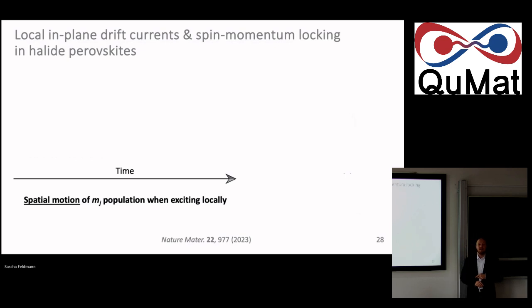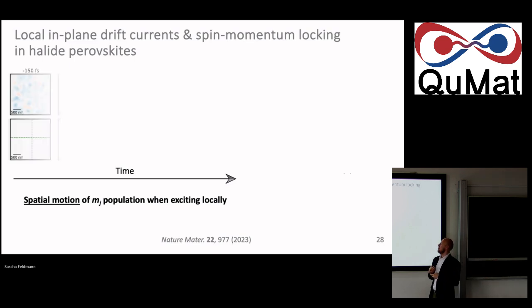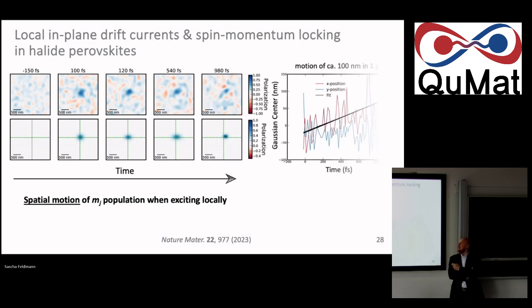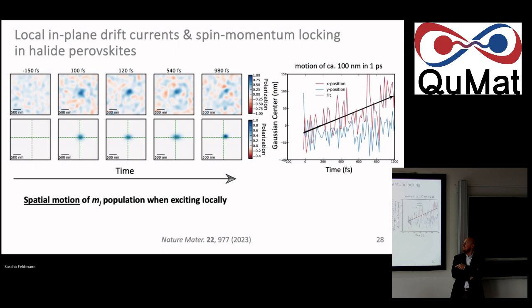We can now also do another experiment where we locally initiate such a spin population and then look at globally how it moves in the film. And coming from a, say, PL microscopy background, you would probably expect a rather isotropic diffusion away from the center of excitation, perhaps, and this to broaden up. But if we do this, and I'll show you here the subtracted out response with some crosshair in the center, you actually see that we are moving to the top right corner of this plot. Can everyone see that here?